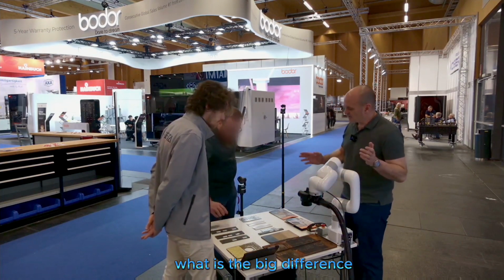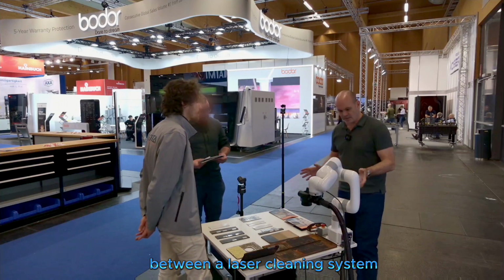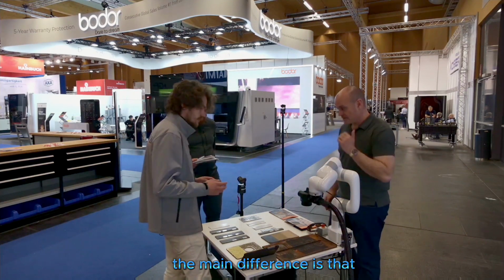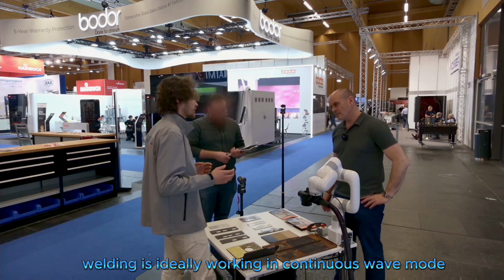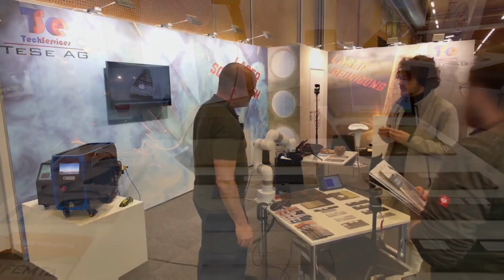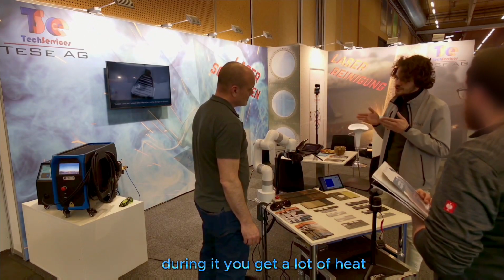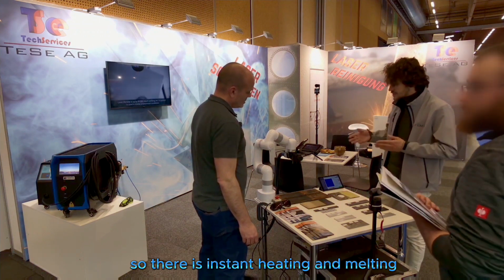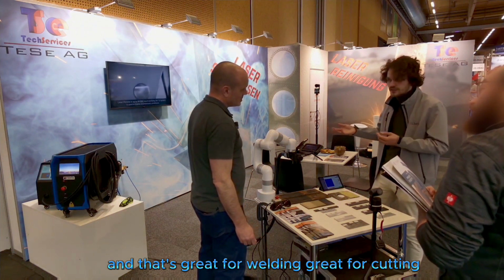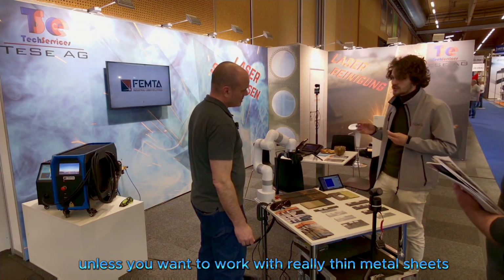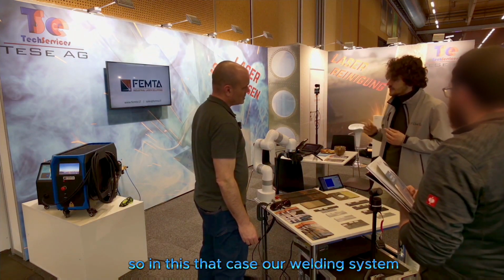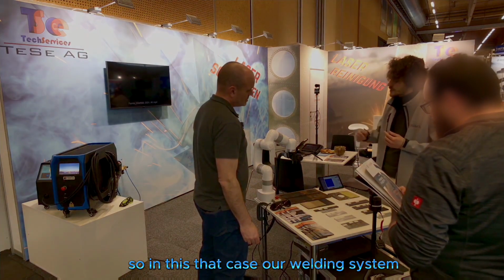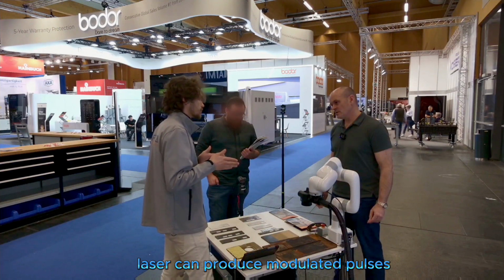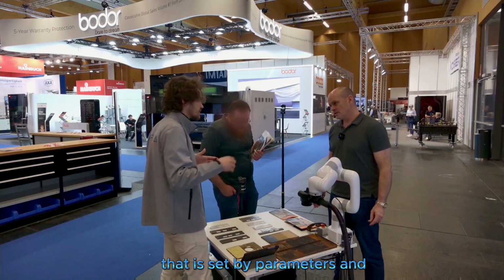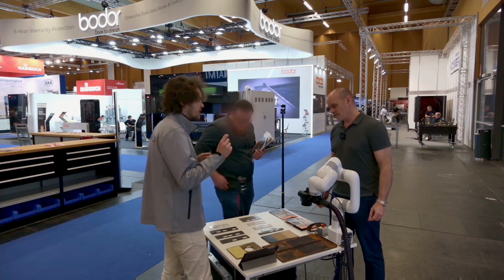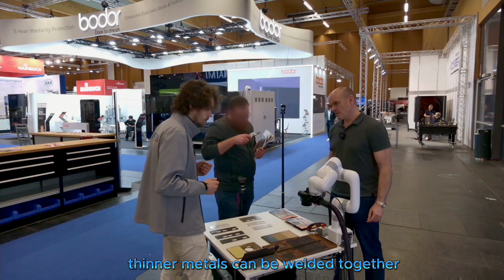And what is the big difference between a laser cleaning system and a laser welding system? The main difference is that laser welding ideally works in continuous wave mode. It means it emits light non-stop, and you get a lot of heat concentrated on a really small space. So there's instant heating and melting, and that's great for welding and cutting, unless you want to work with really thin metal sheets. In that case, our welding laser can produce modulated pulses, working in a certain duty cycle set by parameters, and thinner metals can be welded together.